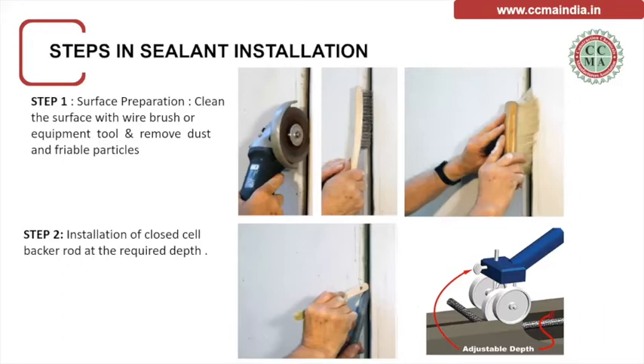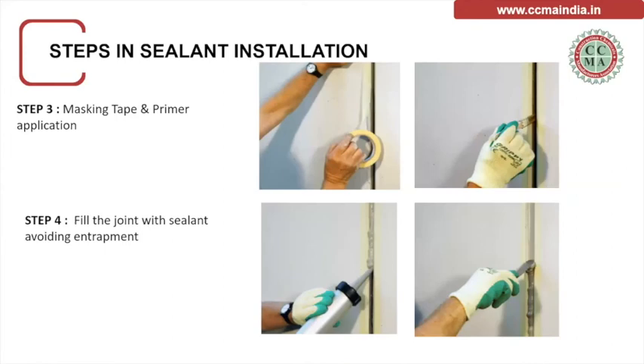Steps in sealant application, very simple. One needs to use a grinder and wire brush for surface preparation, install a closed cell backer rod, and use a backer rod tool to insert the sealant. Then apply masking tape, apply a primer, and fill the joint, avoiding entrapment.